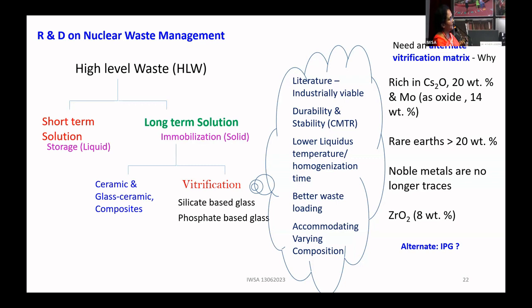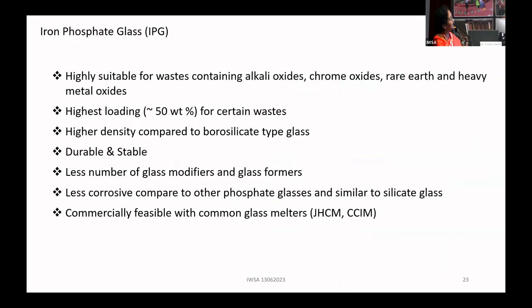You have to take care of the chemical, mechanical, thermal durability and radiation stability. You should have a lower liquidus temperature so that you take minimum time for homogenization, better waste loading, and accommodation of all the compositions required. With respect to fast reactor waste, where cesium and molybdenum content is very, very high, borosilicate glass is not a suitable matrix because it can take a maximum of 2.58% only. Whereas iron phosphate glass, which is an alternate matrix, can take one order higher, 25% of this can be taken, and the salient features are shown here. There are certain ways which can be loaded even up to 50%, and the number of glass formers and modifiers are very, very limited. Although all phosphate glasses are corrosive, an exception is iron phosphate glass, which is commercially feasible with normal joule melters.